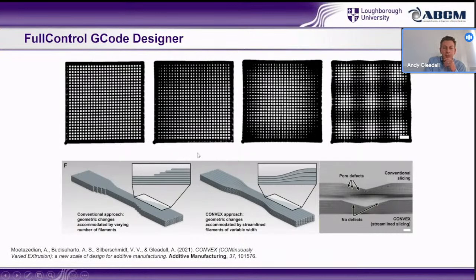This was some research then taking it forwards. The print path is often thought of in terms of X, Y, Z positions, but actually the extrusion width is a really critical aspect that you can control really neatly. So these 4 lattices at the top right all have exactly the same square wave print path. The only thing that's changing is the amount of deposition as the nozzle is moving from bottom to top or left to right. So in the one on the left, the nozzle is printing more on the left, less on the right, and more at the top and less at the bottom.